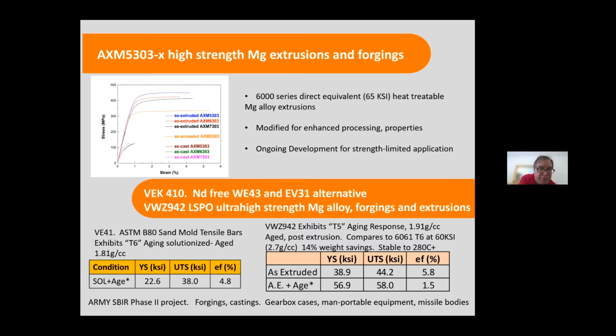Two additional alloys that I'll introduce is VEK 410, which is a neodymium-free WE43 and EV31 alternative designed for low-cost, high-temperature castings. So this is good for temperatures above 200 centigrade to 300 centigrade. It is a very high-strength, high-temperature alloy. And then it is a 22 KSI yield strength, 38 KSI ultimate strength, and that's as a sand casting. And then we have a forging and extrusion alloy,